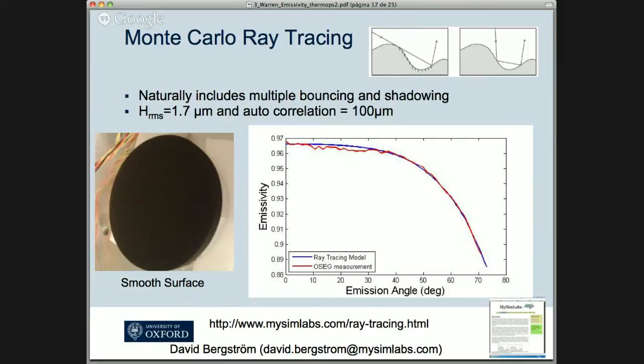So I'll just quickly describe this. This plot here shows you how the multiple bouncing is when it is kicking in, and you can see that it's kicking in from about 40 degrees onwards, which is quite nice because in the plot earlier I was showing where my measurements deviate from a Fresnel-like response is about 40 degrees and onwards.